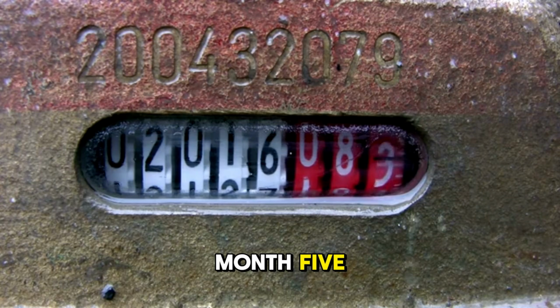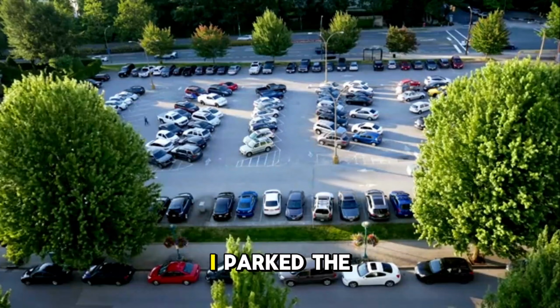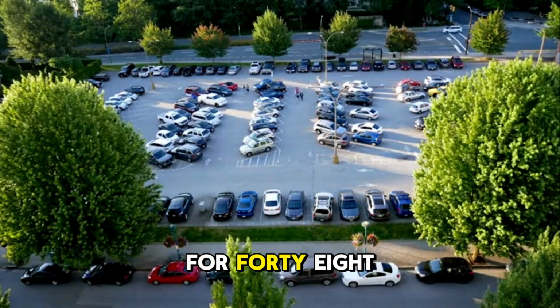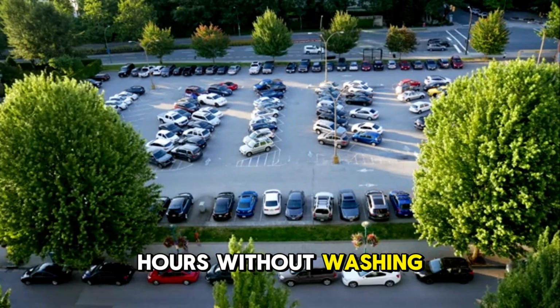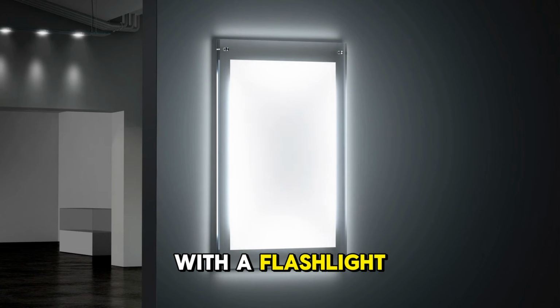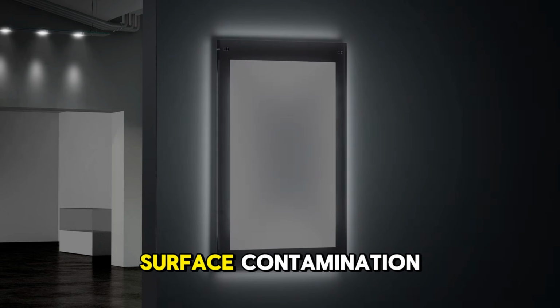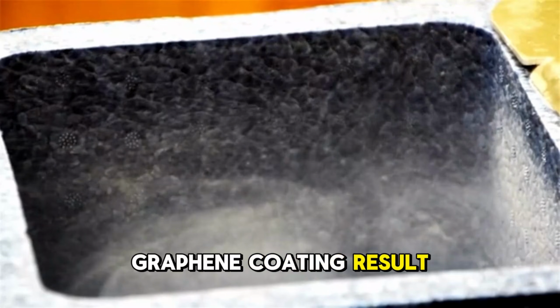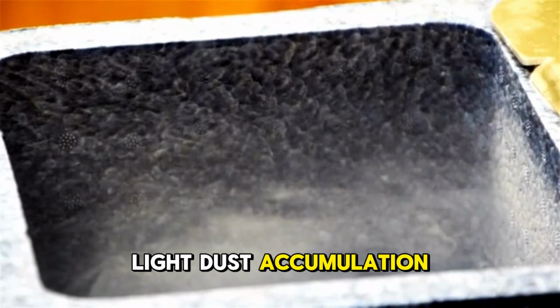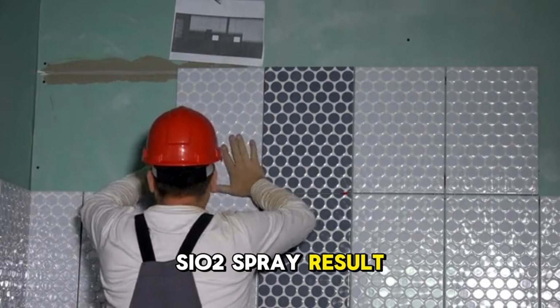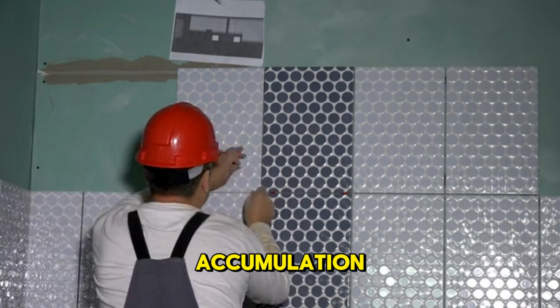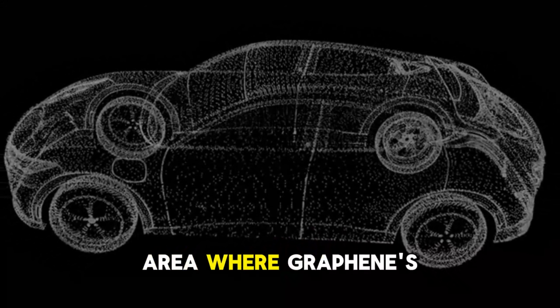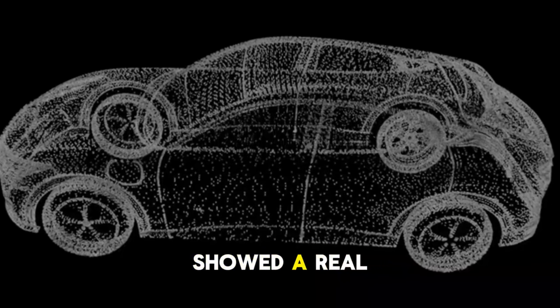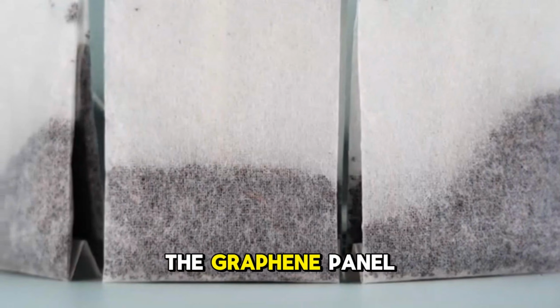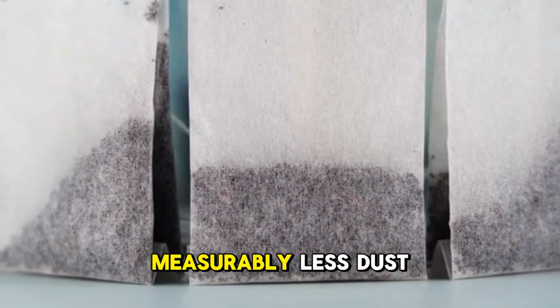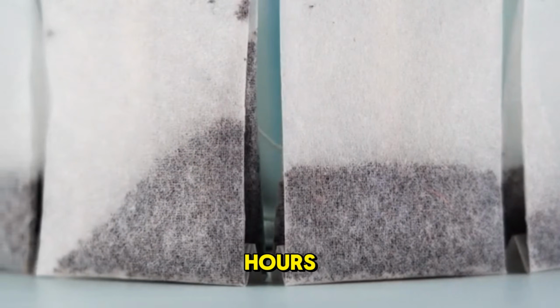Month 5, dust accumulation test. I parked the car in the same spot for 48 hours without washing. Both panels photographed with a flashlight at a raking angle to show surface contamination. Graphene coating result, light dust accumulation. SiO2 spray result, slightly heavier dust accumulation. This is the one area where graphene's antistatic properties showed a real-world benefit. The graphene panel attracted measurably less dust over 48 hours.